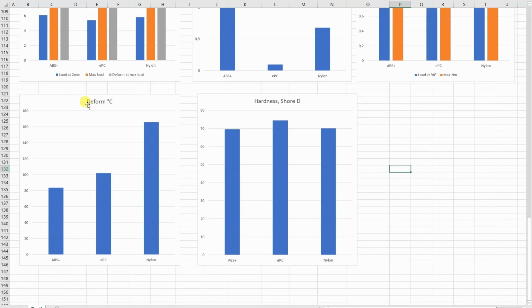And this is the deformation temperature test. This is not standard, soon I will start with ISO 75 following that standard. But anyway, this is a comparison test and something like what I expected. But I was surprised a little bit with this nylon, how well it performs here, until it creeps under constant load, interesting. And this is the hardness, very similar values here.